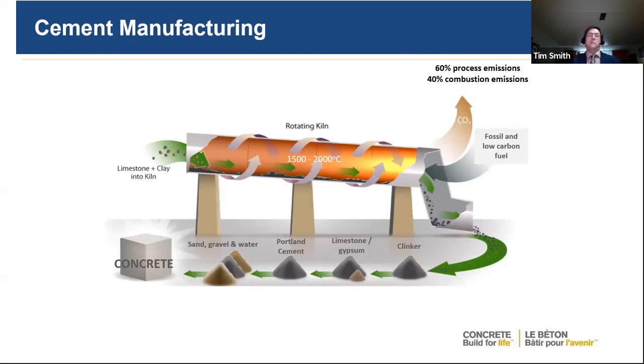So why is that? It's because of the way we create the cement. We have limestone and clay. It's put in the kiln. The temperatures are around 1,500 to 2,000 degrees Celsius in these kilns. This has to heat up the materials to a very high degree. It drives off the CO2 in the limestone. So 60% of the emissions is due to the CO2 being driven off of the aggregates, the materials. 40% of it is through the combustion process of having the kiln at such a high temperature.